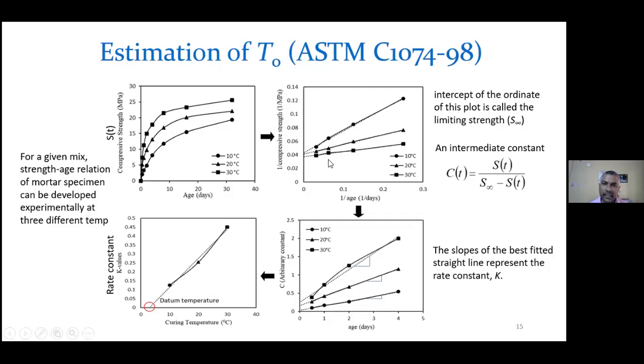So 3 S infinite I will get, and now Ct is an intermediate constant which is equal to St divided by S infinite minus St. Using this formulation I get a plot of C versus t. So just converting the same plot in a different form, I again make best fitted straight lines and take the slope of these 3 straight lines.